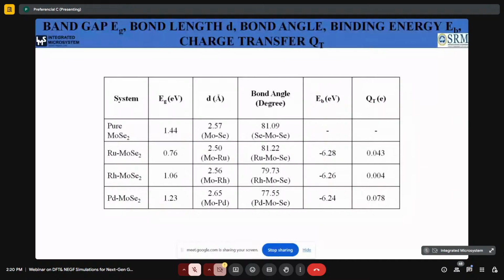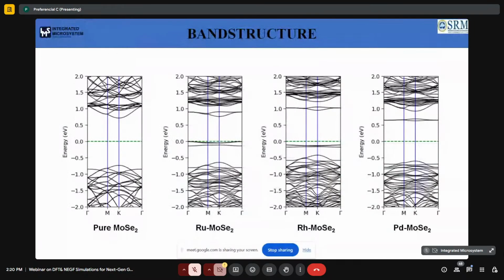The same thing is analyzed by means of the band structure analysis also. In the band structure analysis, very close to this system, and that is a charge transfer analysis, indicating that a reduction in the band gap has happened in the system, and new energy bands are created in the gap when the gases are very close to this system. In addition, if you see the band gap analysis, the energy bands are moving towards the Fermi energy level due to the incorporation of this dopant.